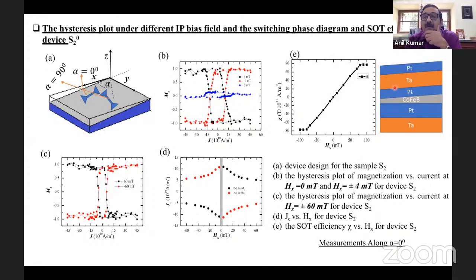Okay, so now I have applied a very small thickness gradient, and now I can make a device which is along the thickness gradient direction or perpendicular to the thickness gradient direction. Now, if I do the measurement along the thickness gradient direction, I still see that I need a magnetic field to be applied to get magnetization reversal. So if you look at the switching phase diagram, at zero applied magnetic field, there's a gray area, meaning I'm unable to switch the magnetization.